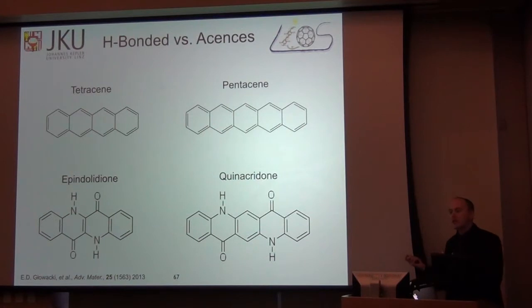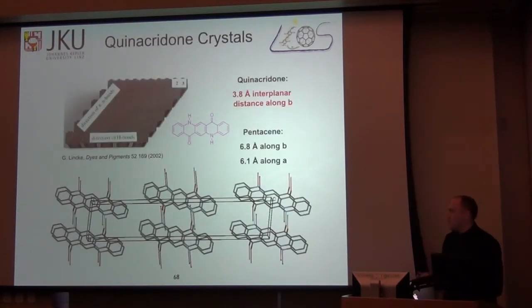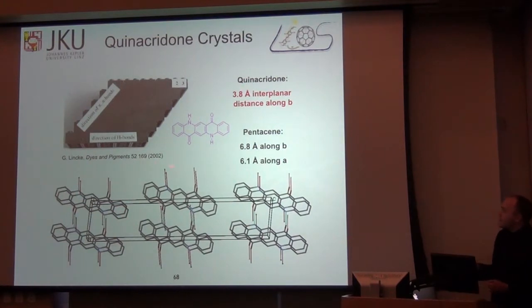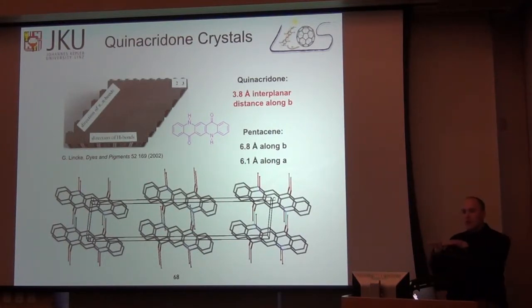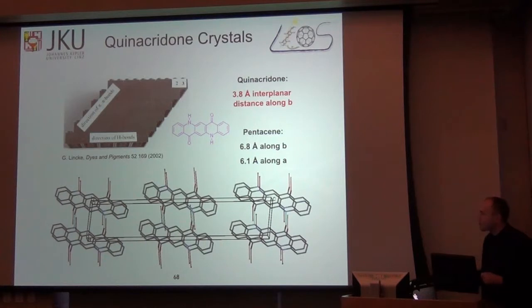So from an initial eye test, you would look at these molecules and say, those are not going to be good organic semiconductors, let's not look at them. But we did look at them. And one of the reasons is that, similar to the TIPS pentacene that we presented before, the hydrogen bonding causes these molecules to form long chains of planar molecules. And then those chains sit right on top of each other in what's called a brick-in-the-wall configuration. And so we have very cofacial and very tightly packed molecular crystals of these guys.